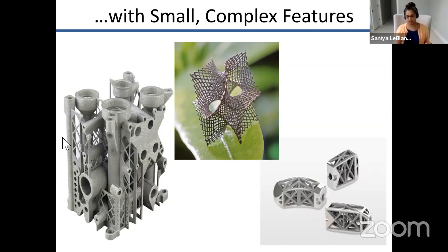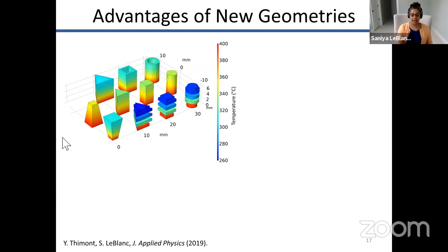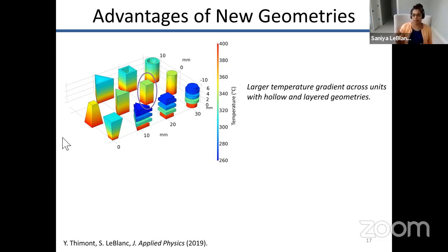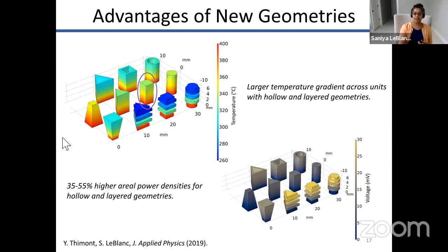And so we thought that this was very conducive to what we wanted to do with thermoelectrics. The benefit here is that if we were to make different thermoelectric unit geometries with this technique, we can compare really simple geometry. Additive manufacturing would allow us to make layered structures or structures where the interior is hollow, as opposed to this one that's circled right now, which is the traditional cuboid type of leg. And what we found is that larger temperature gradients will occur across units that have these hollowed or layered geometries, and that you can get a 35 to 55% higher areal power density for those layered or hollow geometries that you could create with additive manufacturing. So I'm really excited about moving forward with additive manufacturing.